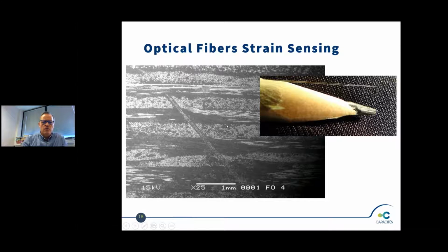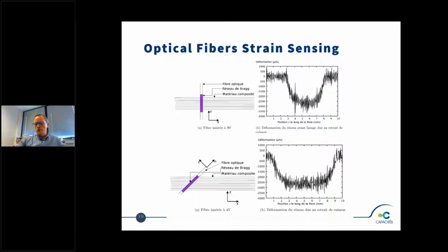embedded in the material. So this optical fiber was a big promise to be able to go inside the material and check some properties. But we ran many tests just to figure out if what we were measuring was true or not. So we embedded some optical fibers across the thickness, perpendicularly or at 45 degrees. And the surprise is to measure between the liquid state and the solid state deformations, strains, up to minus 3,000 microstrains. So it means that we have 0.3% of thickness reduction measured by the optical fibers. And this was quite a big surprise. Now we are not surprised anymore because we master that.